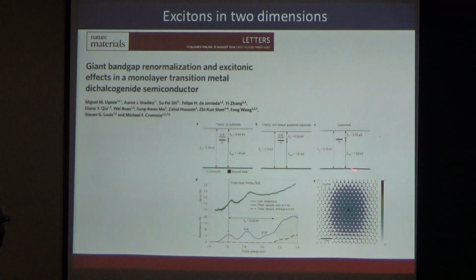Also, the binding energies of these excitons depend on the substrate on which you are putting the material, because the screening will be different. And they had actually also calculated it for no substrate, and for a substrate which is bilayer graphene, and their binding energies are different.